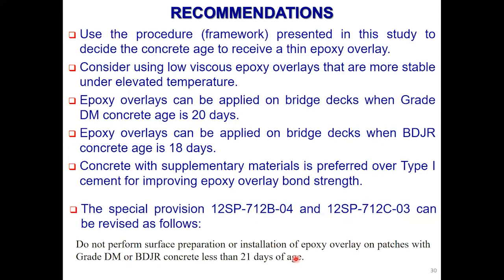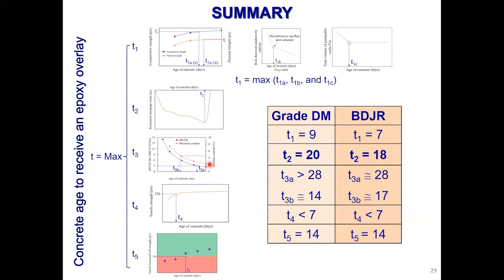So this is the framework that we use to evaluate the concrete age to receive an epoxy overlay, because our objective was to look at whether we need a procedure or a set time. So this shows that we cannot go with a set time because it depends on the mix design and the exposure conditions. Because of that, we can say we need a procedure, and this is the framework, or the procedure, that anyone can use to evaluate the application age. And we see better performance with low viscous epoxies. So because of ease of application and a little better bond, we recommend that.